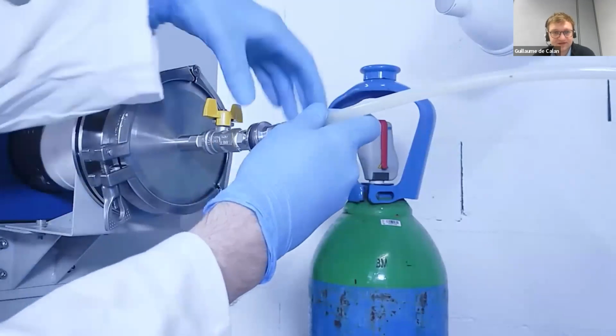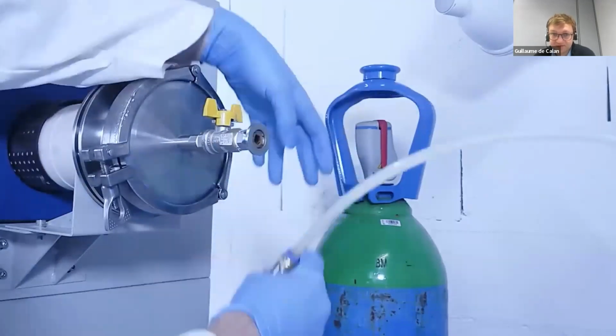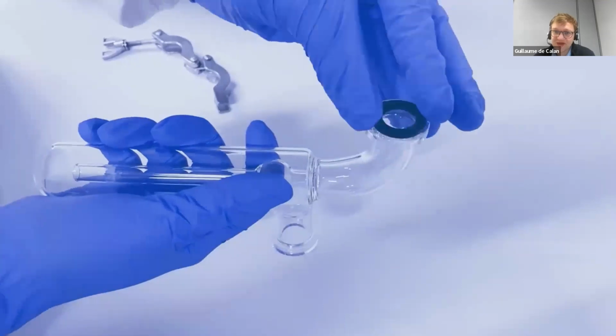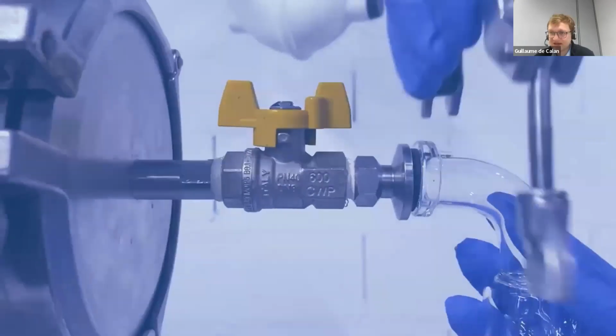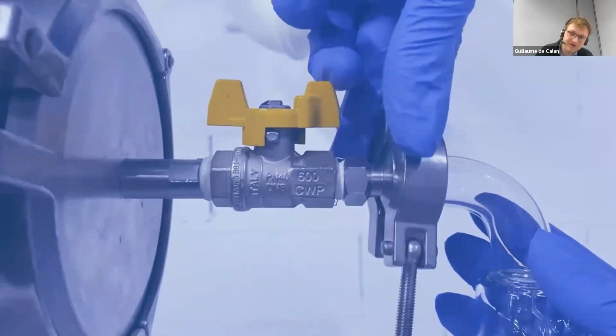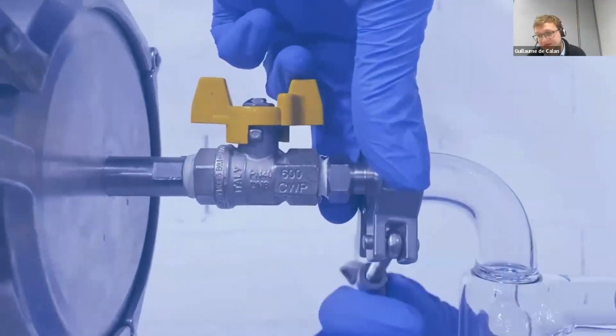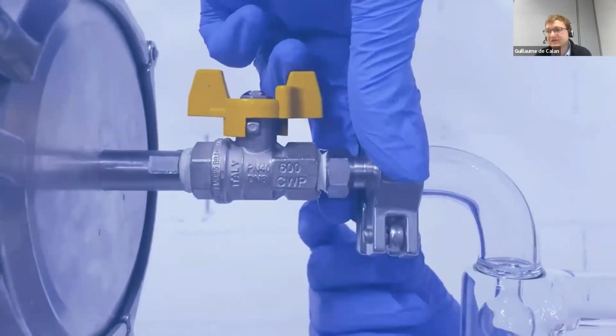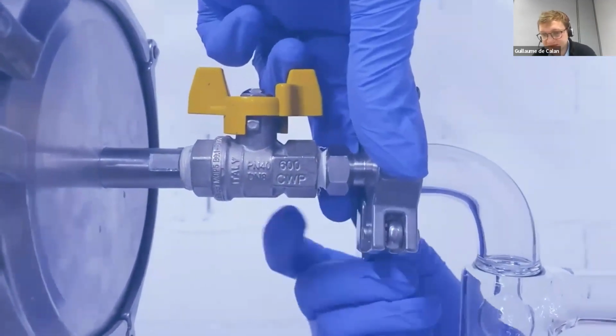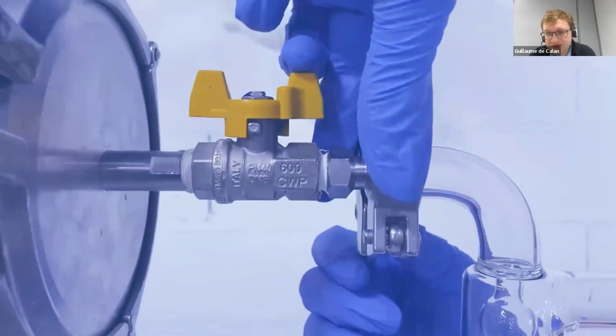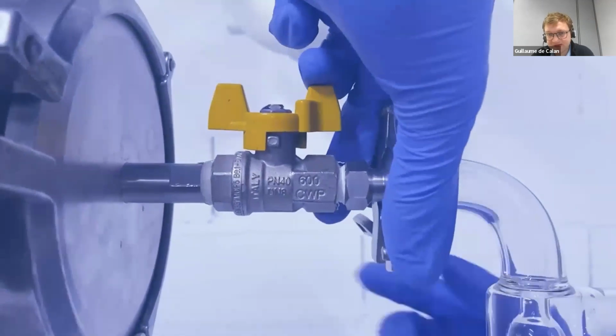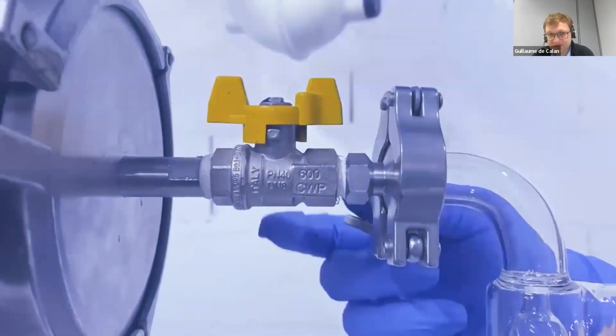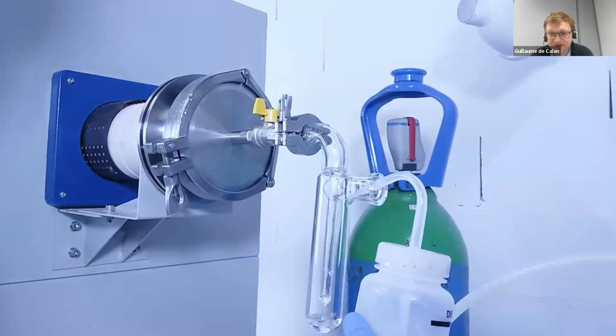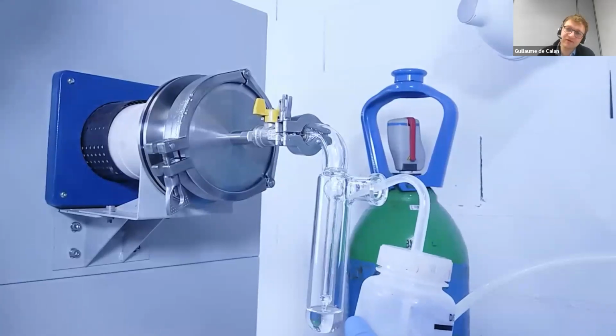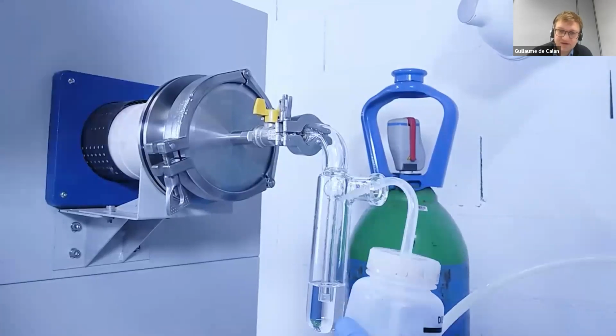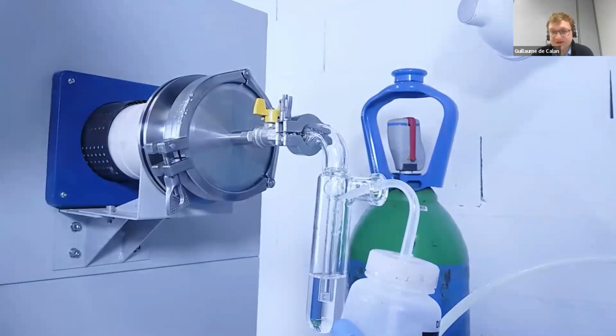On the other side, you can see that it's closed at the moment. On the other side, we will put what we call a bubbler, which makes sure that you don't have any leakage, that you don't have oxygen coming the other way around. So on one side, you have the gas supply, and on the other side, you have this bubbler, which will guarantee that you have something which is completely gas tight. The way this works is that you fill the bubbler with water, making sure that air doesn't go through in the wrong direction. This is crucial.